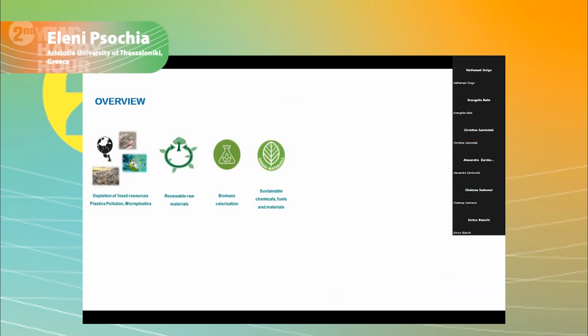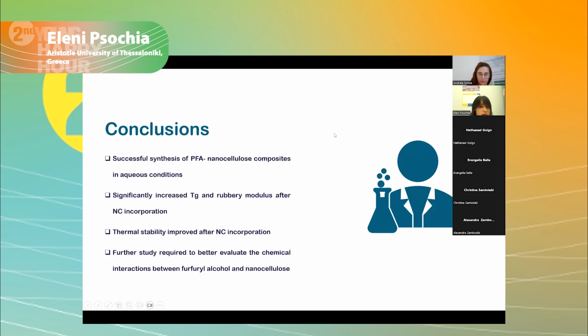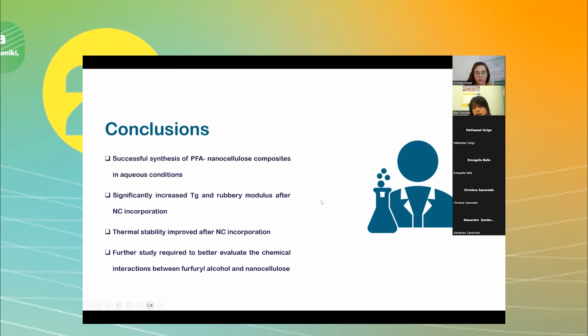So today, the two major problems that we are facing, which are the depletion of fossil resources and, of course, the plastics and microplastics pollution, are urging us to turn to the use of renewable materials. So to conclude, we successfully synthesized PFA nanocellulose composites in aqueous conditions. We had a significantly increased glass transition temperature and rubbery modulus after the nanocellulose incorporation. We had improved thermal stability of the materials, but we have to further study the materials in order to better understand what kind of interactions we have between furfuryl alcohol and nanocellulose.